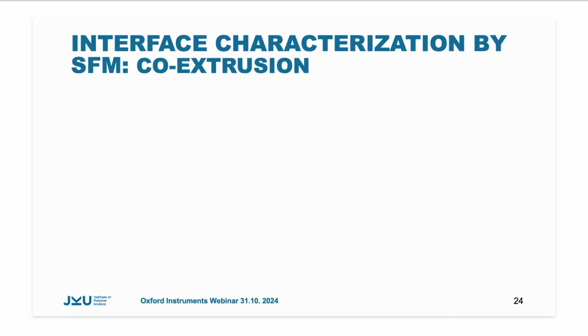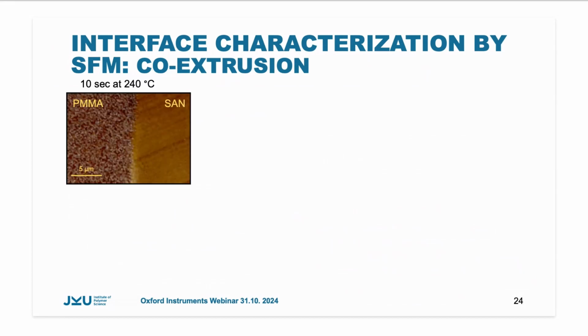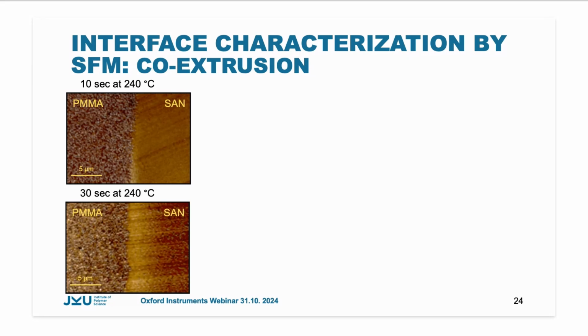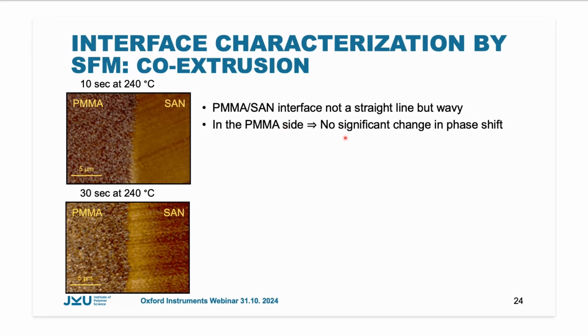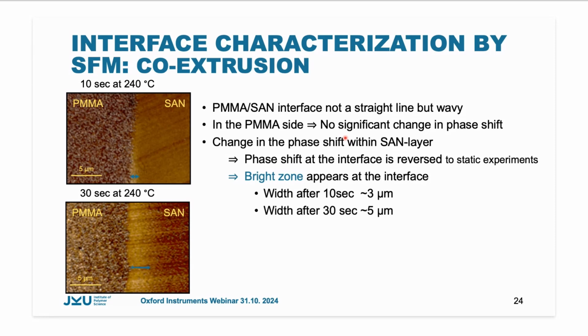Our last topic now is to characterize the interfaces using scanning force microscopy. Therefore, we compared samples in contact for 10 seconds at 240 degrees C and 30 seconds at 240 degrees C. What is similar is that we have the two different polymers, which could be nicely discriminated. But when you look into a little bit more detail to the boundary between the two polymers, this is not a straight line anymore, but it becomes wavy. At the PMMA side, we do not have a significant change in the phase shift, similar to what we observed for the static experiments. On the SAN layer, what we see is that the phase shift at the boundary is reversed to what we observed in the static experiment.